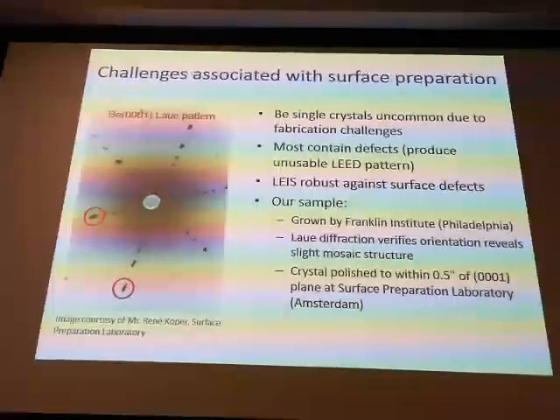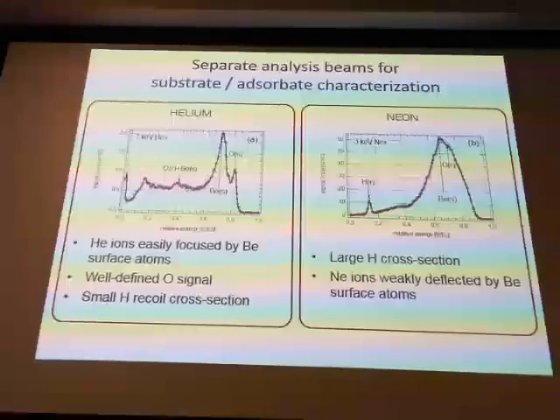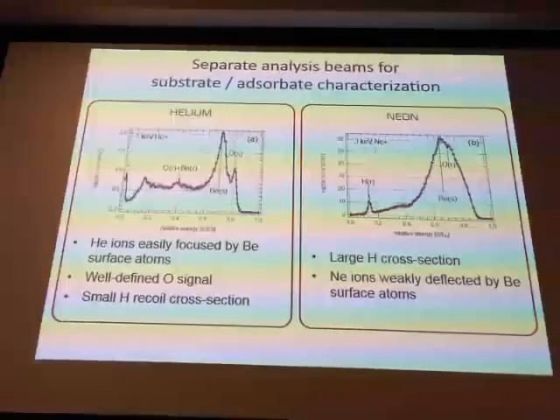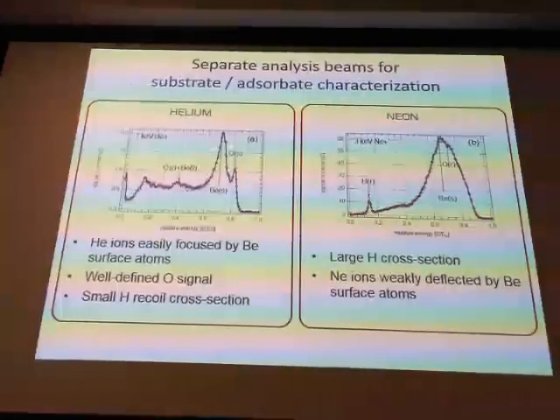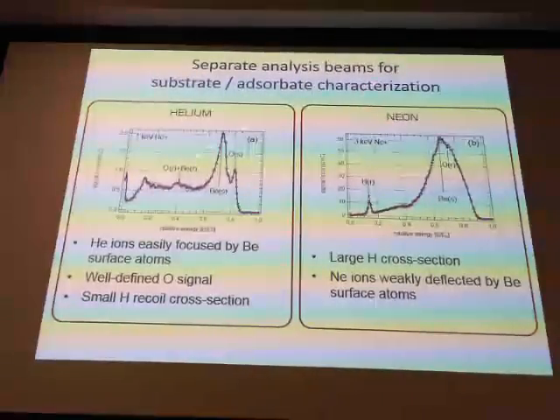It's a material that, due to the hazards associated with working with it, there are not a lot of really high-quality single crystal samples available, and so there hasn't been a lot of surface science work that had been done with it. And so what we did is we used two types of ion beam analysis using helium and neon low-energy beams to characterize the substrate structure and then the adsorbed hydrogen structure.